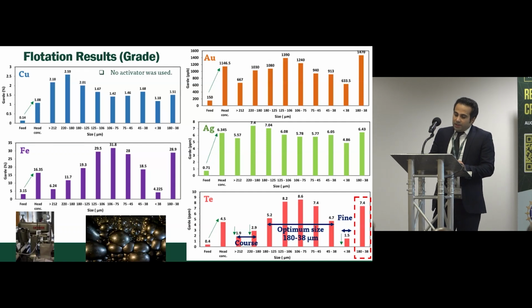Looking more closely at the tellurium bar chart, we can observe that the highest concentration of tellurium belongs to the intermediate size fraction, ranging from 180 to 38 micron. We conducted a flotation experiment with the optimum size. The results were promising, showing that the concentration of tellurium reached 7.4 ppm.